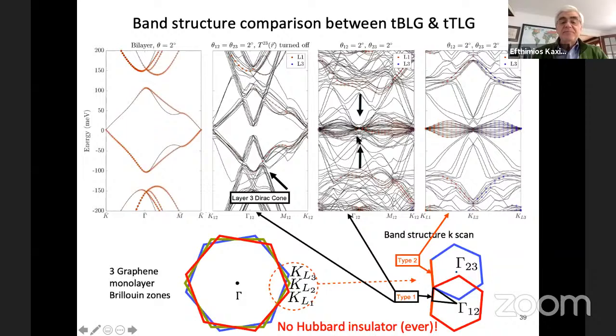Here the flat bands are interspersed, cross-linked with other bands. So this much more complicated situation gives us the idea that things can be more flexible in trilayer graphene. The superconductivity at higher temperature is very promising. And because of no gaps anywhere, you see here in bilayer graphene, you have gaps. So you can isolate these layers and produce this correlated behavior, the Hubbard insulator. Here you have no gaps anywhere because of the many more available bands that cross each other. So no Hubbard insulator. So the physics is different. Not only is it more complicated, more flexible, but even more challenging and interesting to understand.